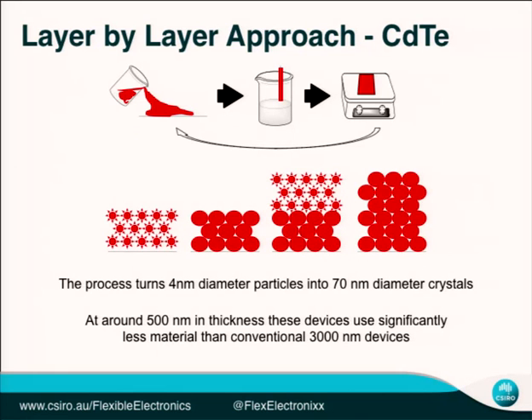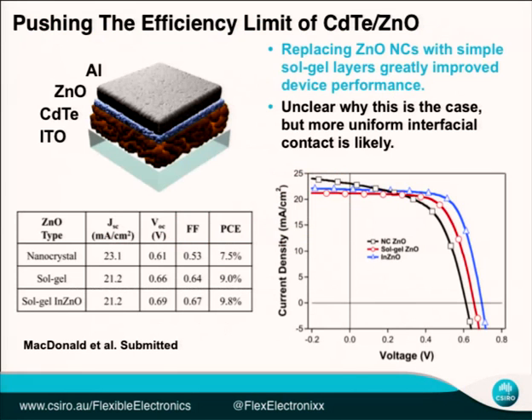So we can make these inorganic solar cells from solution, from the nanoparticles. And we end up with a film that's much thinner than the devices that are made using traditional ways, which is by closed space sublimation. As far as the performance of these go, we've made a few other changes, and this is the structure that we have to them. But we've now got these devices having efficiencies of about 10%, which is comparable with what people get from much thicker devices, but it's a simpler manufacturing process. So again, this is a proven technology that we're developing a new low-cost process to make, where it's all from solution and all in air. So we think that this goes in parallel with our organic work about developing materials and processes for printed solar cells.